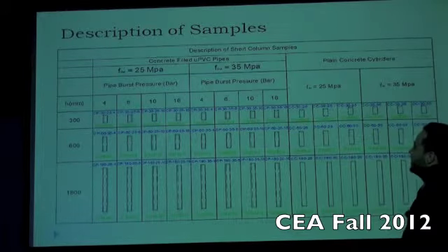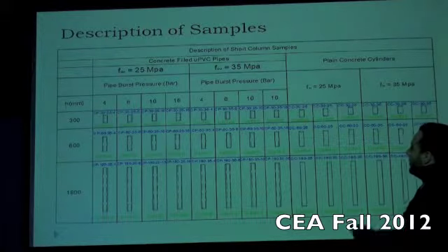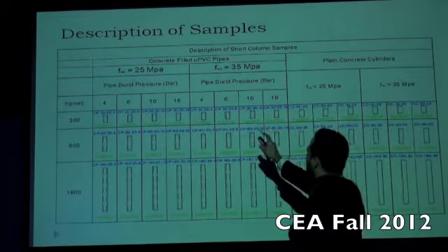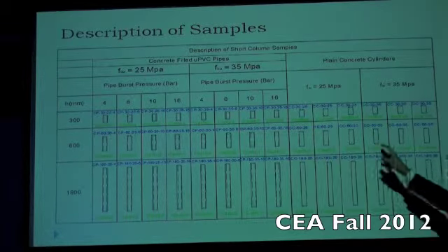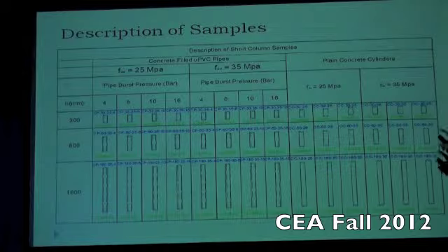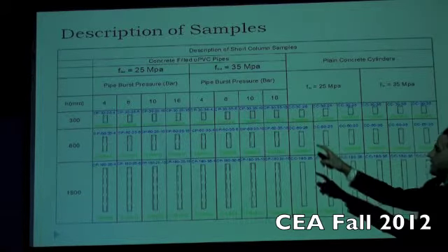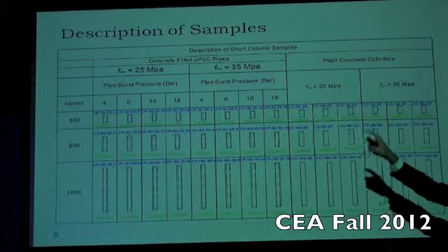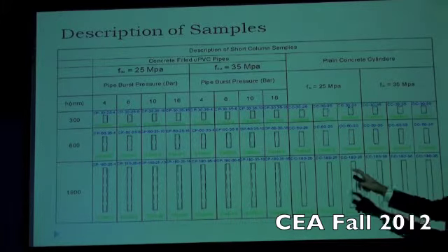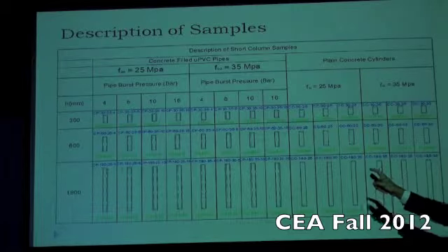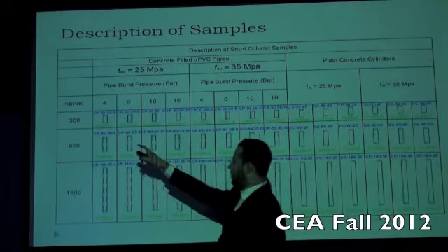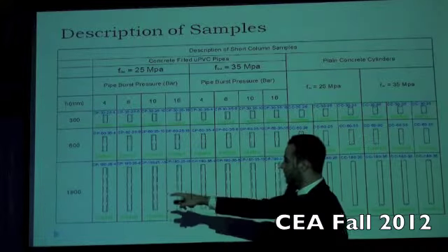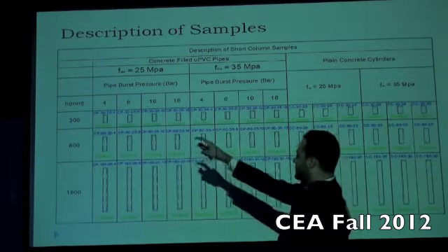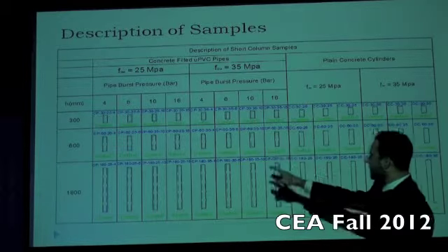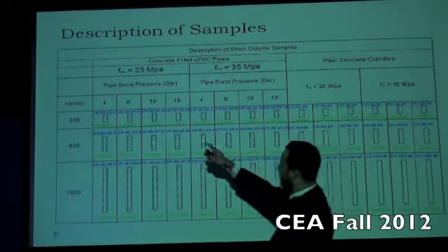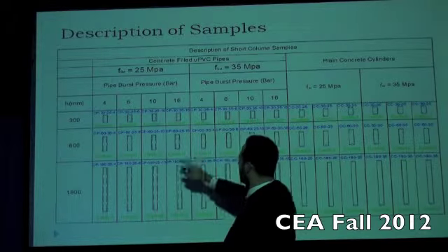Here is a table that shows all the samples we have. As I said, we have completely filled UPVC pipes, and another one, plain concrete cylinders. We have different FCU, concrete strength, 25 megapascal and 35 megapascal. These are the short column samples. Here's 30 centimeter, 60 centimeter, and 180 centimeter. And these are the different bars: 4 bar, 6 bar, 10 bar, and 16 bar.